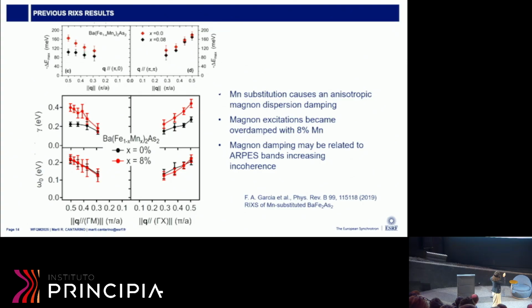So when you look at the pi-pi direction, the excitations have more or less the same energy with doping. But when you look at the pi-0 direction, the excitations have a smaller energy with doping. The pi-0 direction is the iron-iron direction, so the dilution with manganese was damping the iron-iron specific, iron-derived excitation. And RIXS, as I said, is a resonant technique, so I'm only looking at the magnetism derived from the iron.